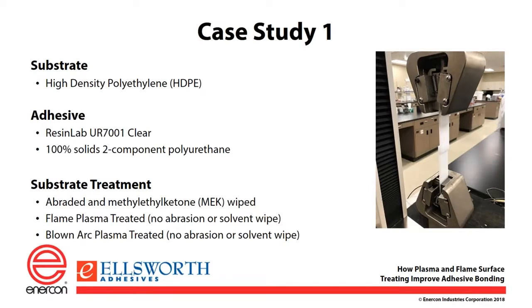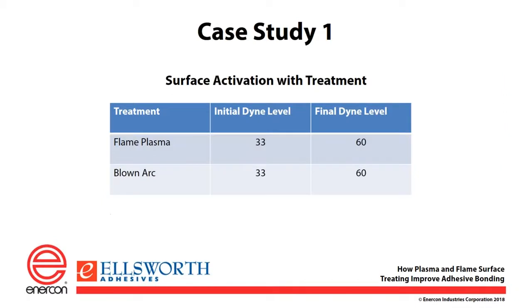Substrate treatments. One of the substrates was abraded with methyl ethyl ketone wipe. So we have an abrasion, so we're roughing up the surface and we're increasing the surface area. And methyl ethyl ketone will actually attack a substrate and make it a little easier to bond to. Another treatment involved flame plasma treatment. In this case, there was no abrasion or solvent wipe on the panel. The only thing that was done was the flame plasma, and we also did a blown arc plasma treatment where, once again, there was no abrasion or solvent wipe. Before treatment, the substrate had a Dyne level of 33. After treatment, we had a Dyne level of 60 in both cases.